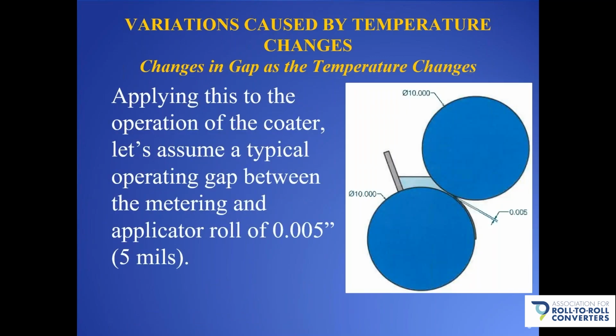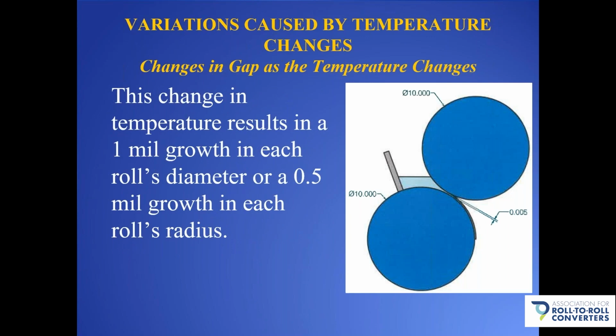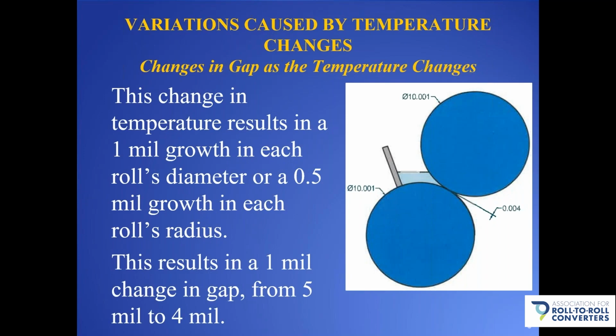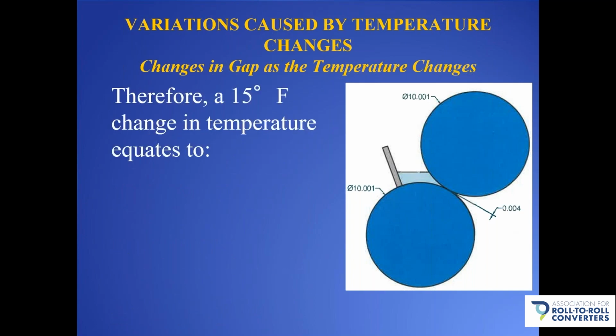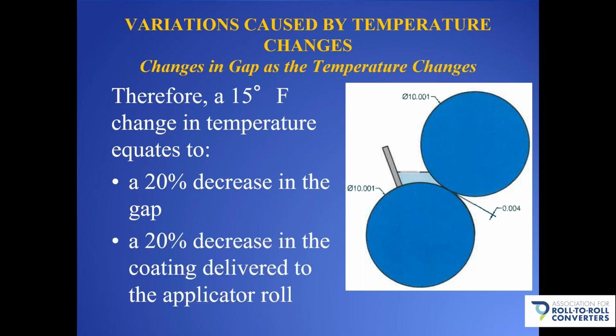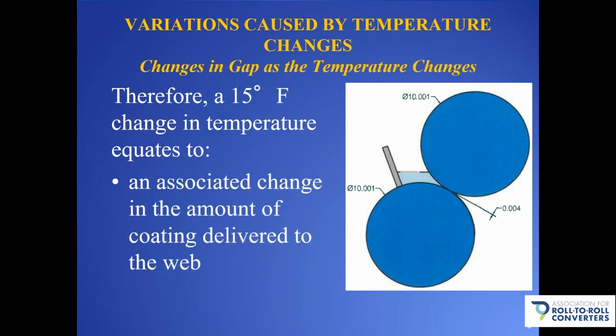So let's look at how that affects things. Let's assume at the start of the day, we set our gap at 5 mils, which is very typical for a reverse roll coater. As the temperature changes, the rolls' diameters change by 1 mil, as we said, where the radius changes by a half mil. So the two rolls' radiuses grow toward each other by a half mil each, resulting in the gap changing from 5 mils to 4 mils. So this 15-degree change in temperature equates to a 20% decrease in the gap from 5 mils to 4 mils, and therefore a 20% decrease in the amount of coating delivered to the applicator roll, and an associated change in the amount of coating being delivered to the web.